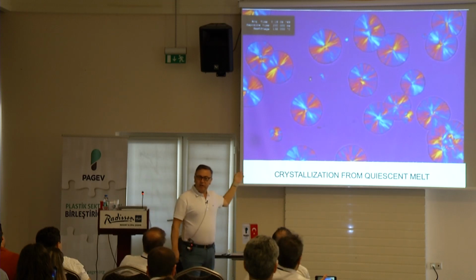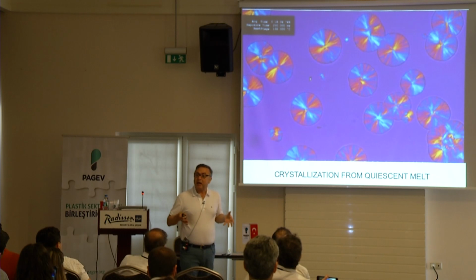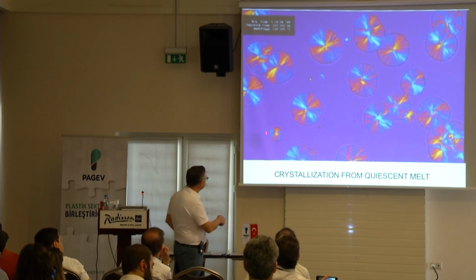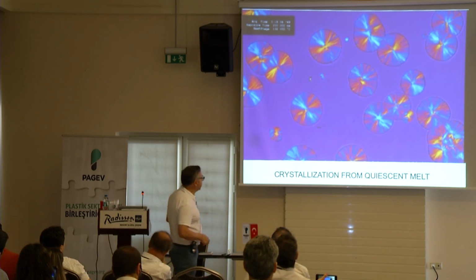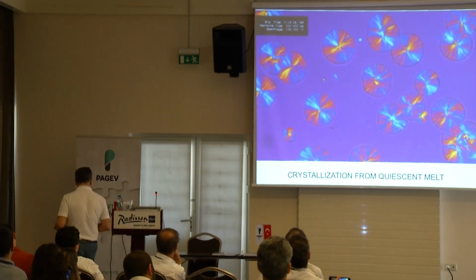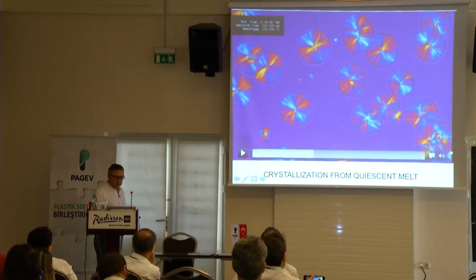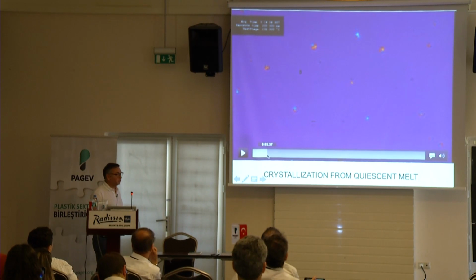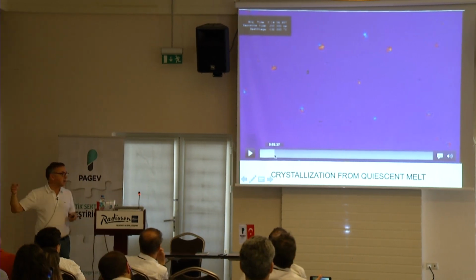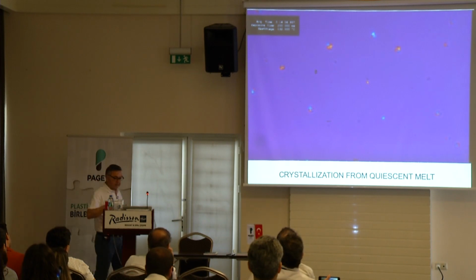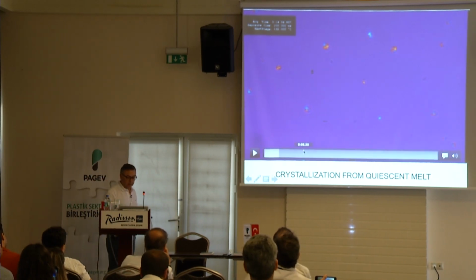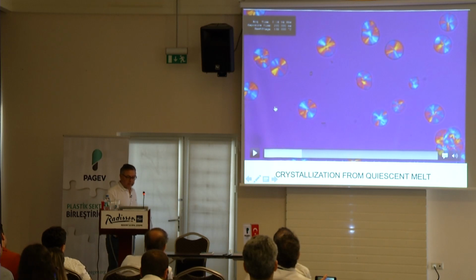The reason why they're all the same size, because they started at the same time, which is an important point. They all started at the same time, right? If there was a size distribution, then, see, this started later. That started later, that started later, but several of them started together. And some already sort of impinged and merged together. So in the early stages of crystallization, they are not aware of each other, right? Like here. They don't care. It doesn't exist. They just do what the thermodynamics tells them. They just simply grow.